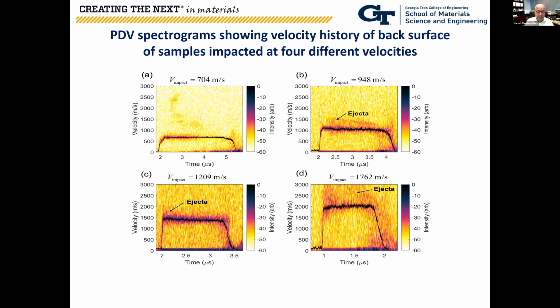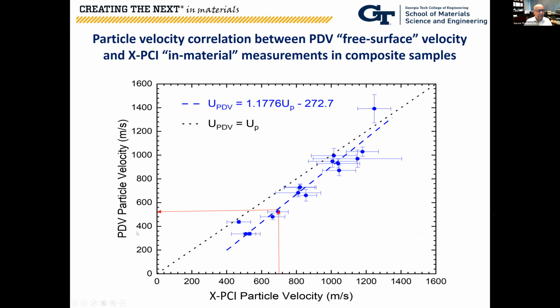Nevertheless, for the sake of correlation, we consider what that plateau or peak velocity represents in terms of particle velocity, because the PDV gives you the back free surface velocity, which is correlated to particle velocity. So if we plot the particle velocity obtained from PDV as a function of the particle velocity captured from XPCI, the data points show how the two correlate. If there's a one-to-one correlation, the dashed black line gives the response, meaning the PDV particle velocity matches exactly with the XPCI particle velocity.